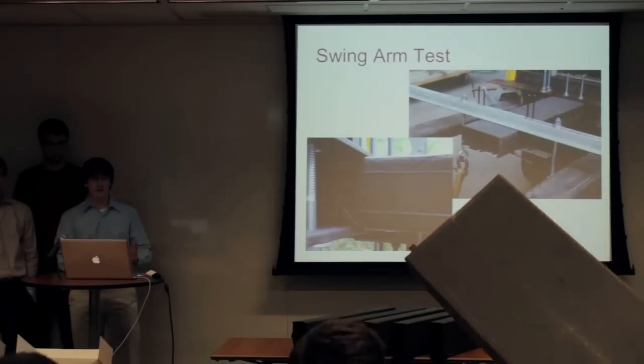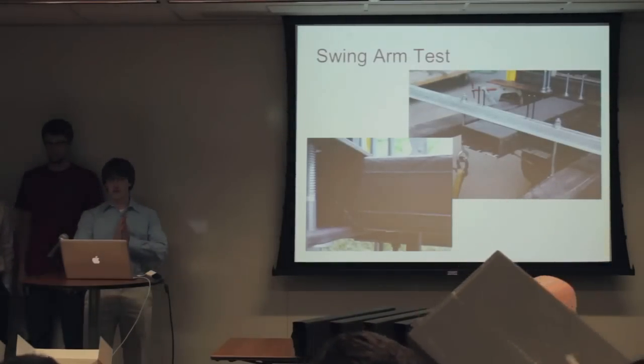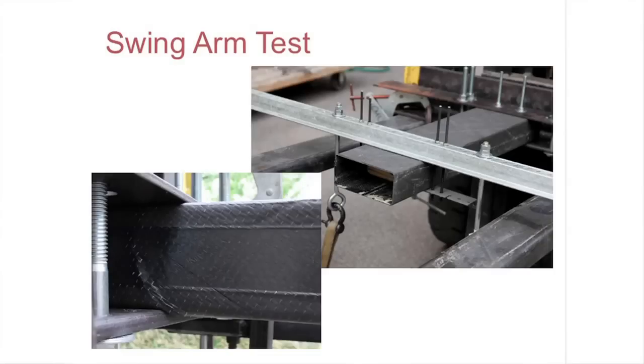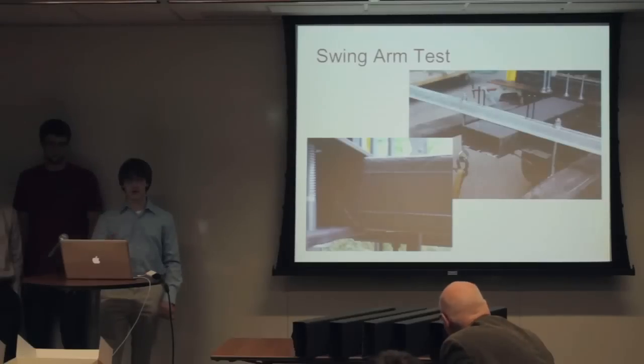So the second test was to sandwich this thing between 2 steel plates, which you can see in the picture on the right, and then clamp that to a forklift, and then gradually raise the swing arm while we have load being applied at the end. And our load, we varied it between 500 and ultimately 600 pounds. And it ultimately broke at 606 pounds, which was much more than the static load requirement, which was approximately 120 pounds.